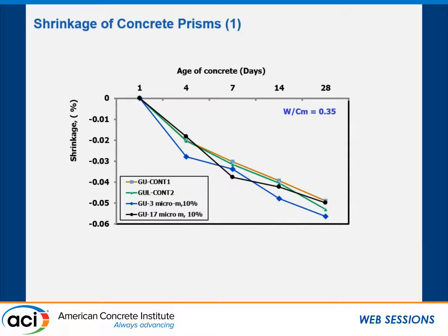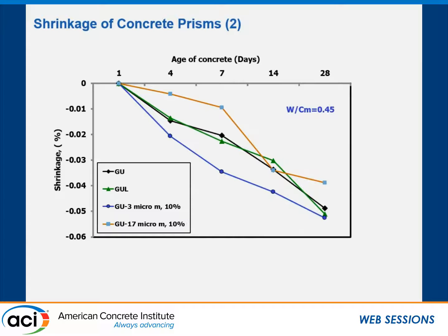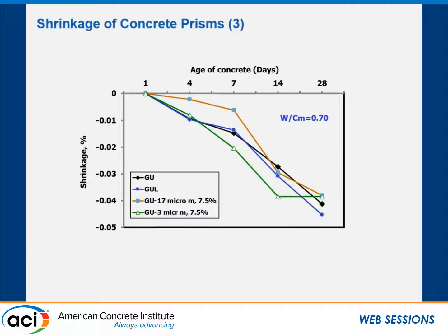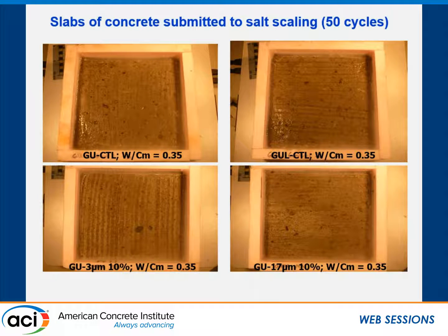That was just a graph of the same numerical results. For drying shrinkage, all mixes showed similar or better results than the reference — this holds at both the 0.35 and 0.45 water-to-cement ratios. The GU and GUL are grouped together, and the two limestone-addition products are also grouped together, with either similar or better shrinkage results.